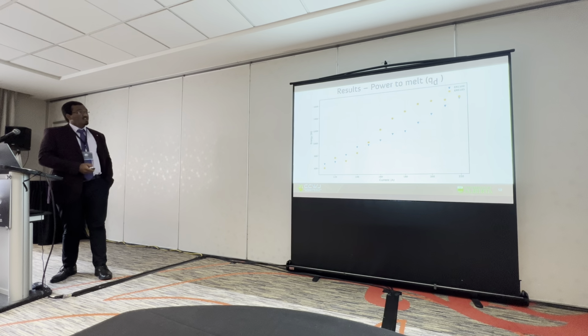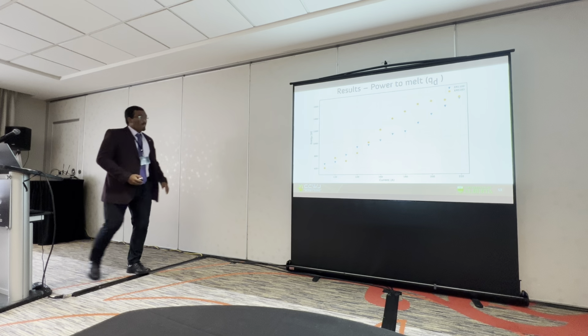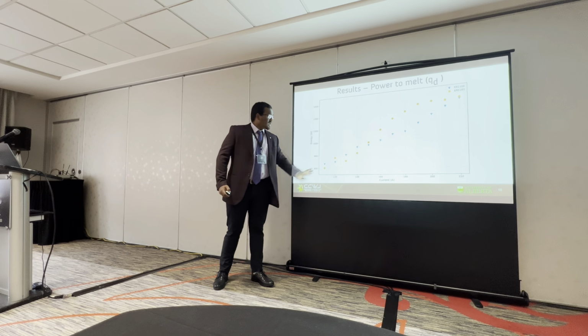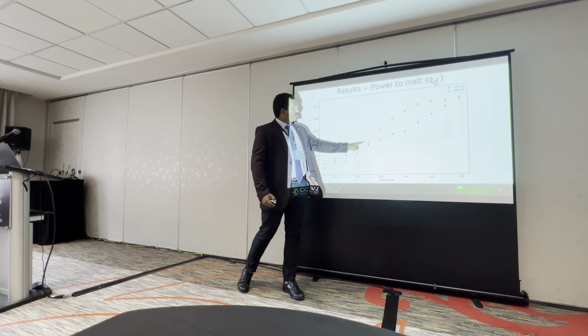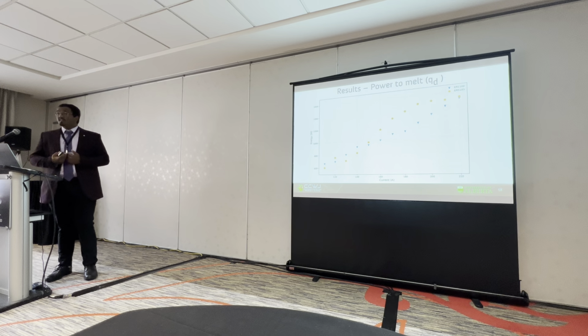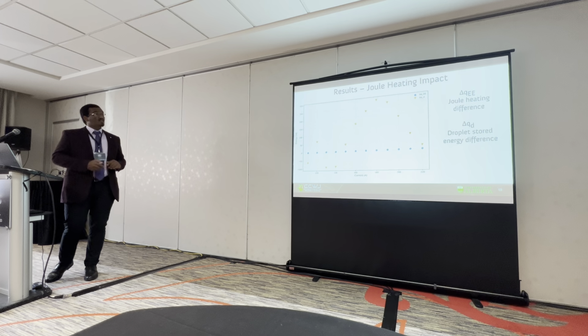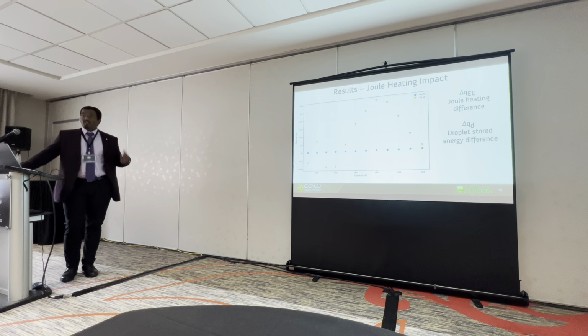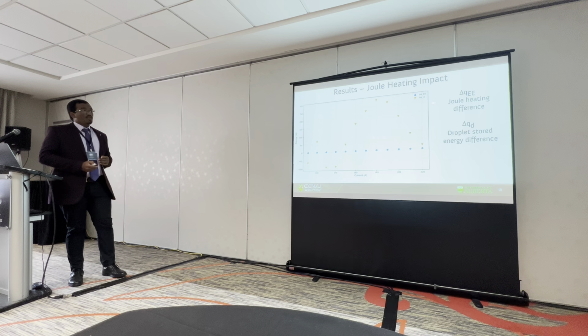Now, when we compare it with the actual power necessary to melt the wire, QD, here we have 5183 shown by the orange circles and 1100 by the blue triangles again. Here you can see that in the initial scenarios, 5183 is lower than 1100 except at 120 amperes. But after that there's a switch in which 5183 becomes higher all the way up through increasing currents. So we have an initial lower power to melt the wire for 5183, then it switches and it needs a lot more power than 1100. That's the only point I want you to remember. So now we can actually compare the results and the Joule heating impact. This graph shows the energy with current, and it represents two things, delta QE and delta QD.